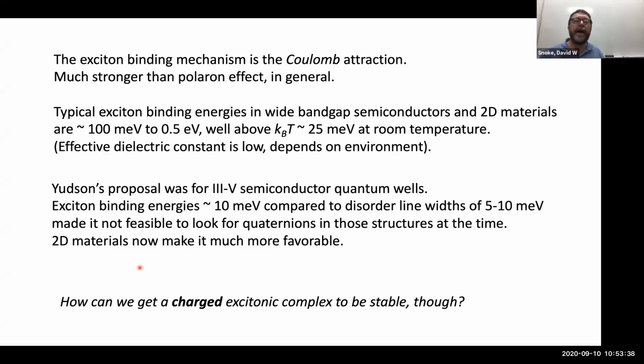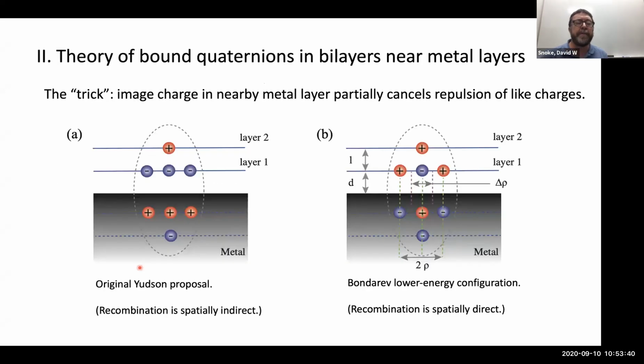All right, so here's the trick that Yudson proposed, and it is to make a bilayer system next to a metal. So this is the real system up here, consisting of, this is Yudson's proposal. You have a doped layer, which has some excess charge, and then you optically excite it so you get an exciton, and the exciton is then bound to 2 extra charges.